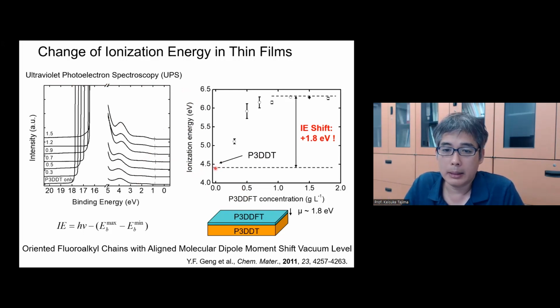So usually, without this surface layer, it's 4.4, and then it gradually, linearly increases with the concentration of this surface layer because of the dipole layer formed at the surface, and then it saturates. It's the same behavior as the fluoride concentration and the hydrophobicity. The important thing is that this ionization energy shift is really large, 1.8 eV. That is almost like changing the electron donor to the acceptor.